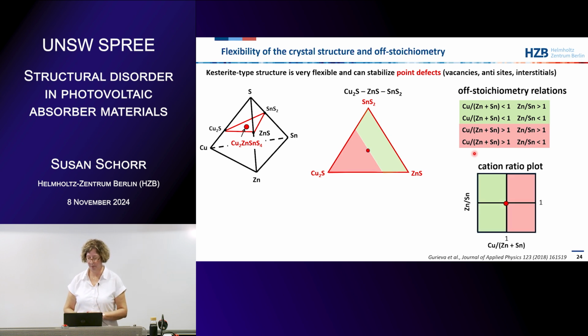So we always use the cation ratio plot to show which off-stoichiometry relations we have. This is copper over zinc plus tin and zinc over tin ratios, and here is the stoichiometric point. Now, where is, for instance, the A-type defect? This is the line for the A-type off-stoichiometry, according to the off-stoichiometry model. This is the composition when you go along this line. The A-type is correlated with copper vacancies and zinc on copper.